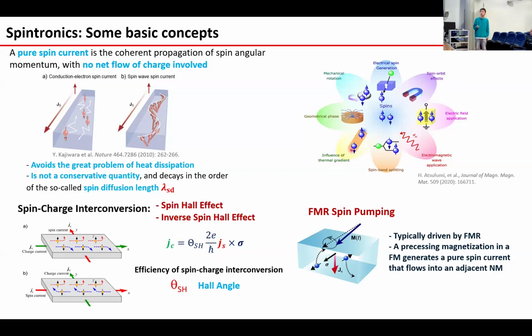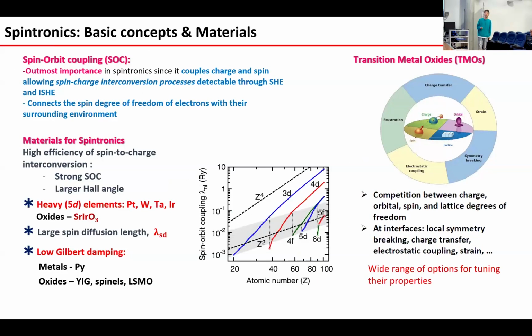And there are many ways to generate spin current. For example, in this figure: spin band splitting, thermal gradient, the spin orbital effect, and so on. In our case in particular, we are utilizing ferromagnetic spin pumping, where the precession of the magnetization in the magnetic field generates a pure spin current that flows into the adjacent normal metal layer. As I mentioned before, spin orbit coupling is very important in spintronics because it couples the charge and spin, allowing the spin to charge conversion process to be detectable through the spin Hall effect and inverse spin Hall effect. It also connects the spin degree of freedom of electrons with their surrounding environment.